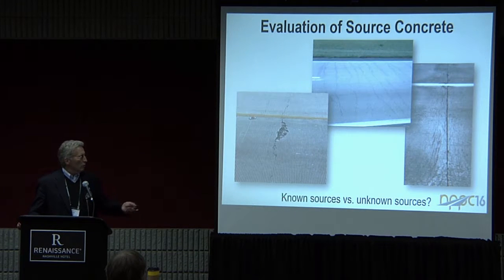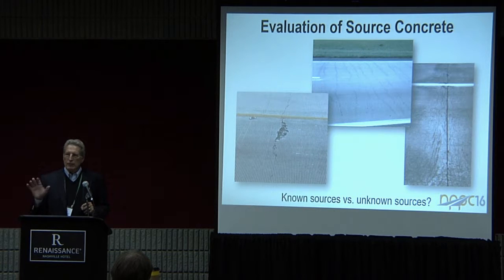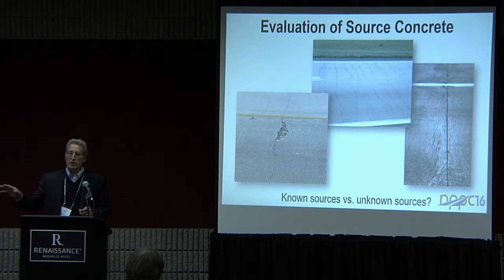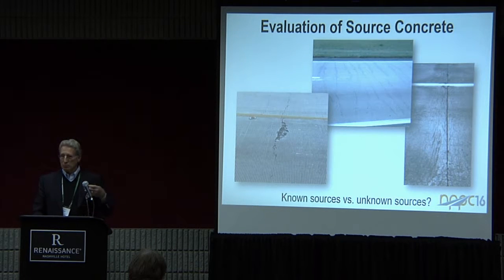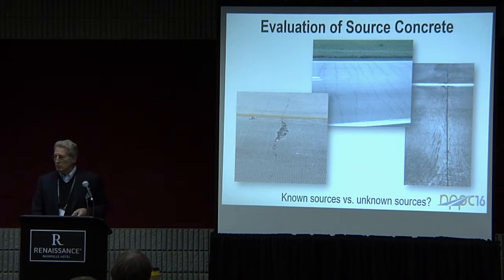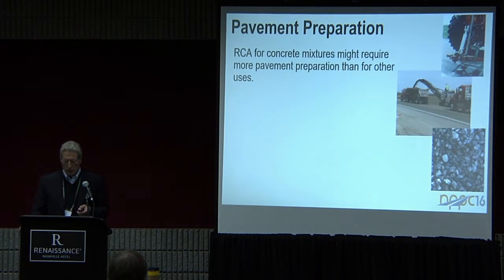Then there's the whole issue of known sources versus unknown sources. A lot of states have got specifications for using recycled materials. A lot of times they're requiring that they be from the pavement that's being reconstructed at that time. If you have an open spec, you want to have some kind of a quality spec on there about where that material is coming from and being able to trace it back, because there are potential problems with building and demolition debris, with using brick, with using gypsum, and other sorts of contaminants that might be present, even into base applications, particularly into paving applications. So know your sources, know where it's coming from, and have a good handle on the quality.